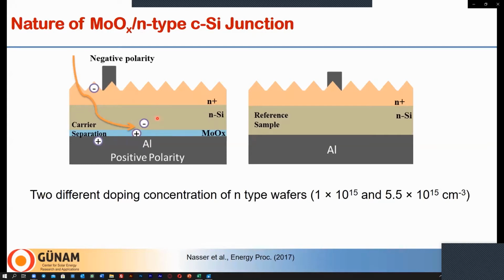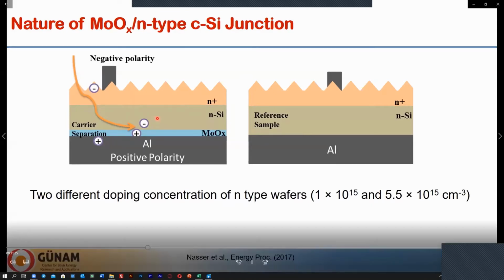For molybdenum oxide, we used thermal evaporation at room temperature to deposit 10 and 15 nanometer of molybdenum oxide. And in order to identify the nature of the junction, we used two wafers to produce these devices. These wafers have different resistivity, one with 1 times 10 to the 15 and one with 5.5 times 10 to the 15. So we have two wafers, one lightly doped and the other moderately doped.